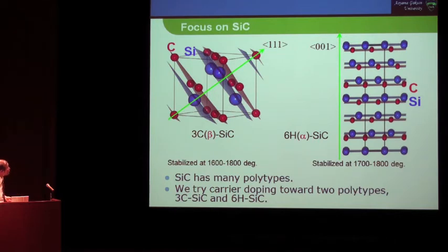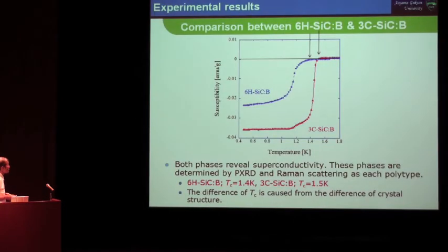This crystal structure is separated by temperature. Under high temperature we get the 6H silicon carbide, boron doped, and 3C boron doped silicon carbide is here. TC is delicately different - this difference of TC is probably caused by the difference of crystal structure.